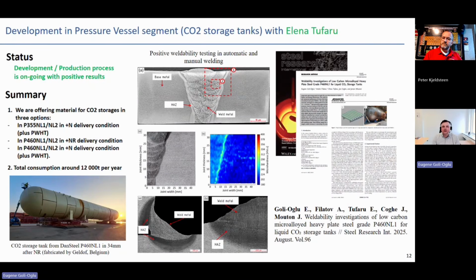Because during the technological process of heavy plate production, when you're preheating the steel, your grains become really big, with a size of, for example, 100 micrometers. And then during the process, you're reducing the thickness, but at the same time you start to deform the plate. With this deformation, in certain regions, grains start to pass through the recrystallization phase. So they are created again, appearing again from small ones, and then start to grow again.